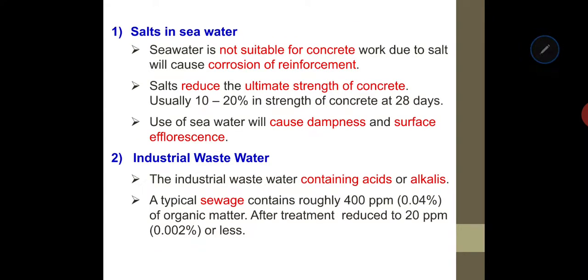For salt in seawater, of course we know that seawater is not suitable to mix our concrete. This is because salt is an agent of corrosion. So if you are constructing reinforced concrete, it will corrode the reinforcement inside your concrete. And also salt will reduce the ultimate strength of concrete. The strength will be reduced, usually 10 to 20% at 28 days. It's very bad, you know.